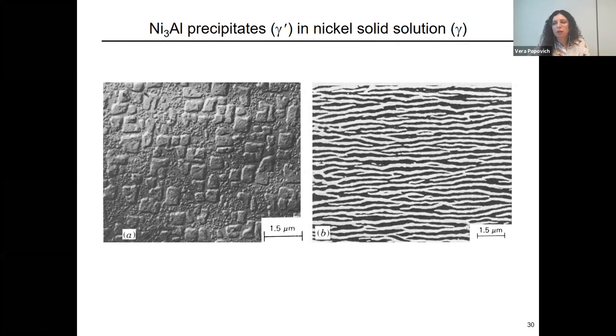Now, why nickel-based alloys and why do we actually look into these gamma prime precipitates? Why do we want to have this gamma prime in nickel-based superalloys? Because we saw that in this cookbook, a lot is done to form this gamma prime precipitate. And this, in this particular case, is Ni3Al, but it can also be Ni3Nb or Ni3Ta, for example, depending on the alloy elements. And these gamma prime precipitates are normally in cubic form because of their characteristic crystallographic structure. So they're formed as cubes.